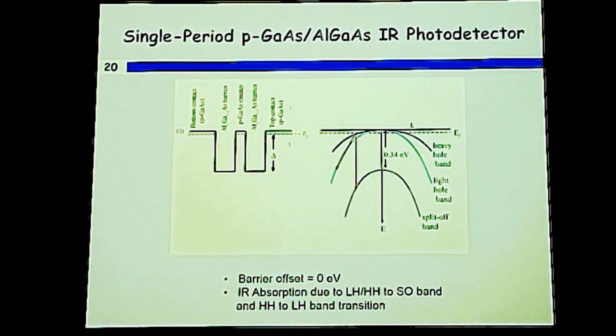So this is the structure that does not have any offset. It detects based on the absorption in the split-off band, from the heavy hole and light hole bands. The energy threshold of split-off absorption is 0.34 electron volt, but because of high peak doping, the Fermi level is in the valence band. So the peak absorption is at an energy slightly higher than this. This energy corresponds to 3.5 micron or so. This peak corresponds to 2.7 micron or so.